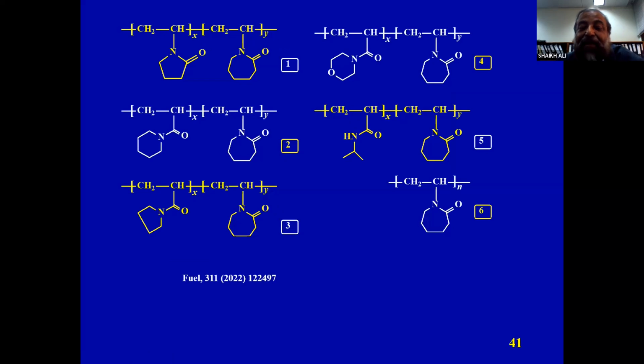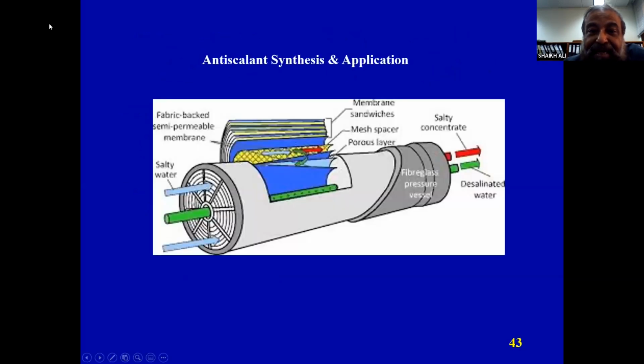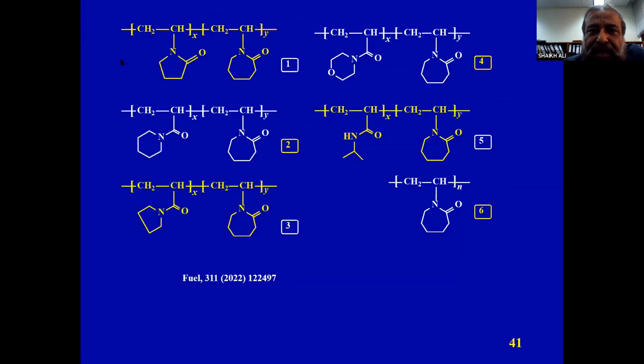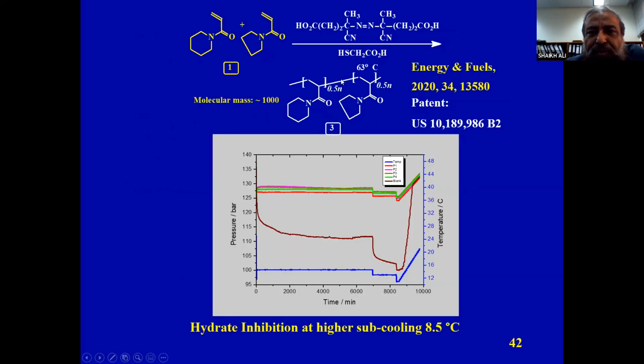We have made about 65 kinetic hydrate inhibitors for Saudi Aramco, and when we made from 1 to 65, we found out that this hydrate, when we made this, number 65, that is the last sample we made, turned out to be one of the best available in the world. Best available in the world.